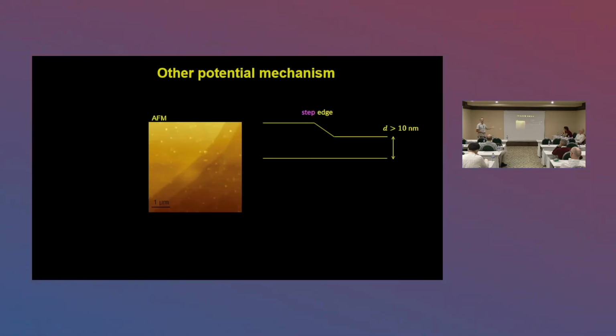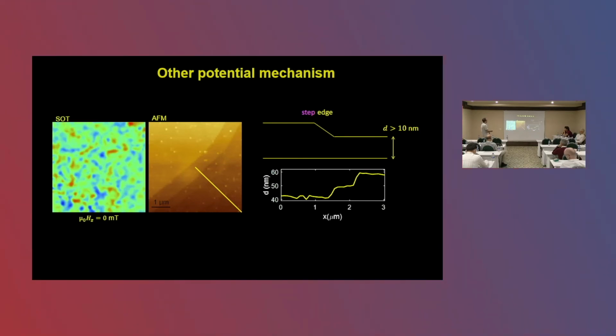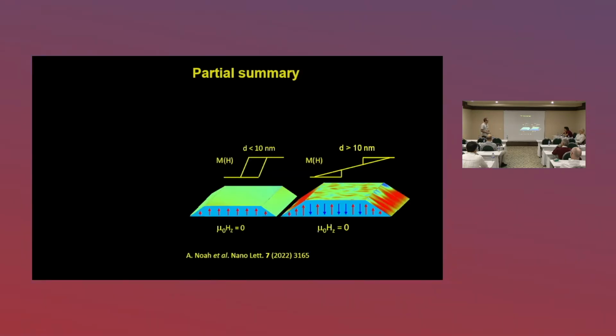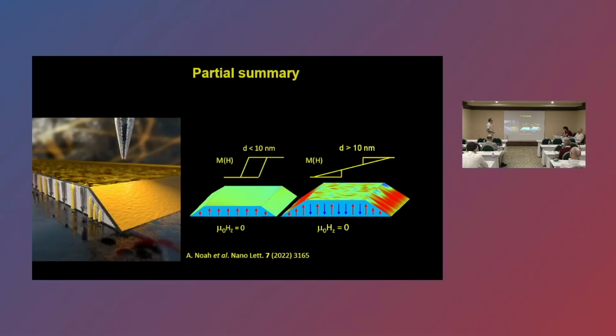And it turns out that we had AFM data of these terraces that happen naturally in these van der Waals materials. You see these nice steps. And this is the image of that area at 0 field. We see absolutely no edge magnetism in the case of step edges. So it really seems that it needs to be at the edge of the sample to be magnetized. So, partial summary: thick films have no magnetism in the interior, only at the edges, and thin films below 10 nanometers or so behave like a hard ferromagnet, or if you want the artist's impression, to remember it better, take it home. So now let me switch gear to the bonus material.